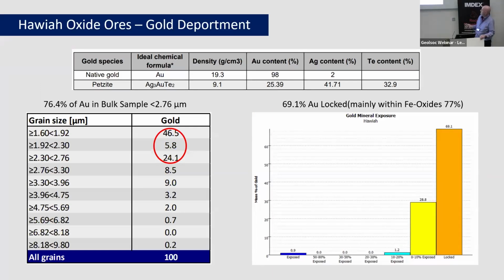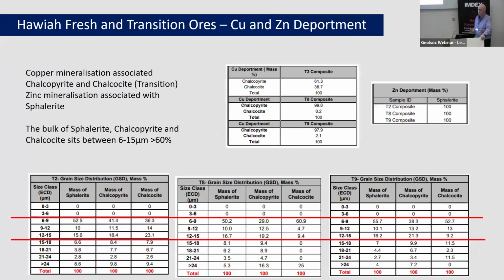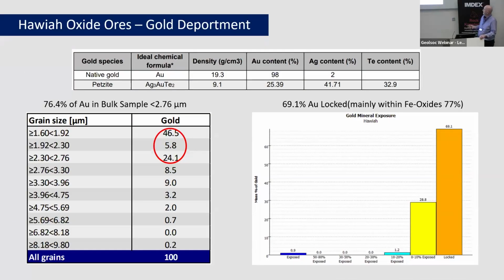If you look at this, it's a gold grain size. You're looking at less than 5 microns. So as soon as you see that, you know you've got problems on extraction. Most gold deposits that leach well, they're down around in here. So as soon as you see that, there should be at least a red flag, if not a bell, that goes off. That doesn't help. There's quite a bit of petzite in there. It does have these tellurides. They don't have antimony in them, which is even worse.